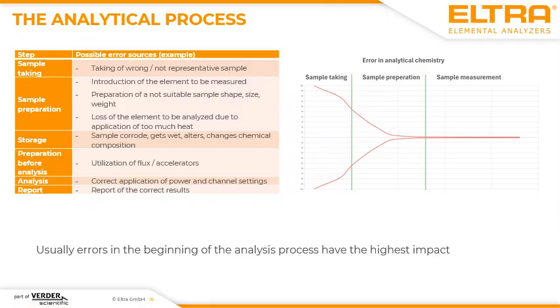Usually, the errors which have been made in the beginning of the analytical process are higher than at the end of the analytical process. Which means, for example, when somebody brings you a powder and says it's an iron-based powder, but it's not, it's a titanium-based powder, then you maybe apply the incorrect settings for analysis, and then you would get strange results.